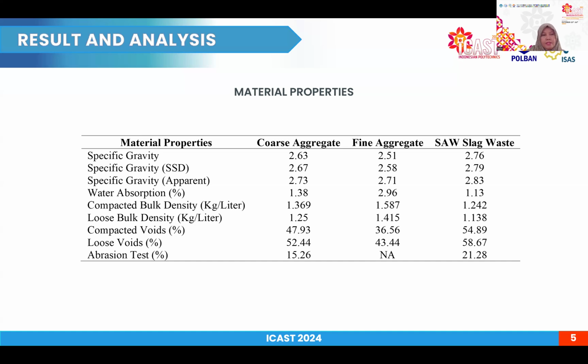Results and discussion. The material properties. Material properties were assessed through specific gravity, bulk density test, and abrasion test on sub-base coarse material comprising coarse and fine aggregates. And SAW slag content was adjusted to the dry weight of each test sample. The results of this property test determine the outcomes of the compaction and California bearing ratio test, which we will examine in the next slide.